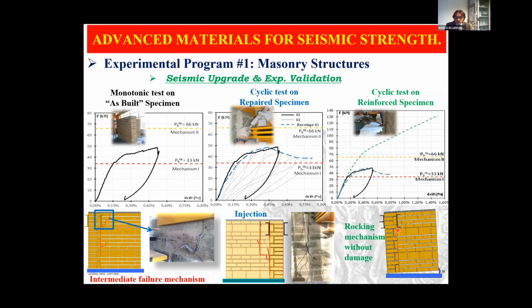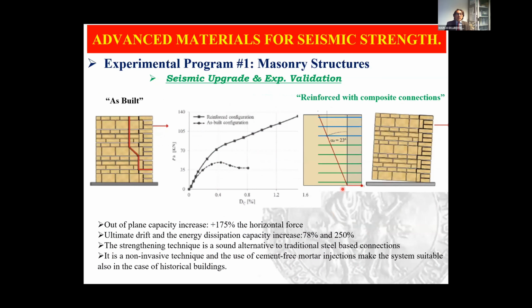specimen, and as you can see, the capacity was increased a lot, and then due to the anchors, we achieved a rocking mechanism without damage, and so without the overturning of the wall. So the as-built had an overturning with a clear crack here. In this case, we achieved the rocking of the specimen just by using this kind of solution.